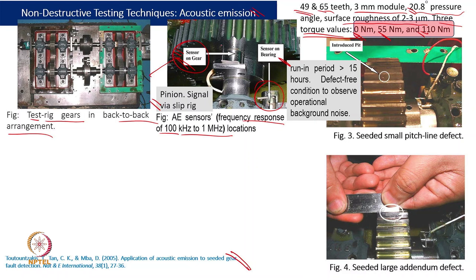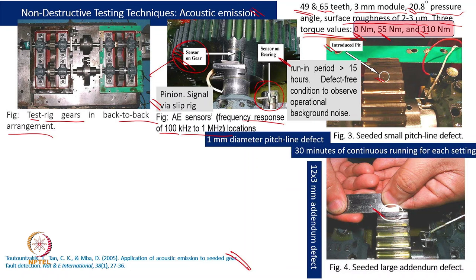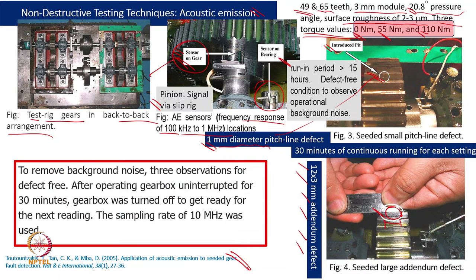That was with a gear that doesn't have any fault. Just to get data, they made a very small pit on the pitch circle diameter on one of the gear teeth, and the other one is a seeded fault of bigger size. One defect of the gear was 1 mm in diameter. And when they used the seeded fault, it was 12 by 3 mm. 3 mm is on this side, that is almost 1 module, and then the width is 12 mm. So this is the addendum they kept in there.